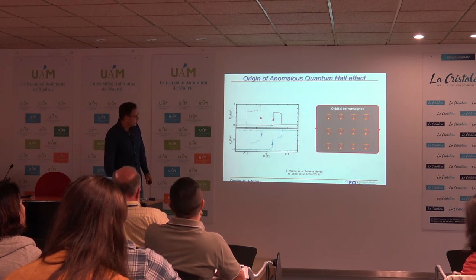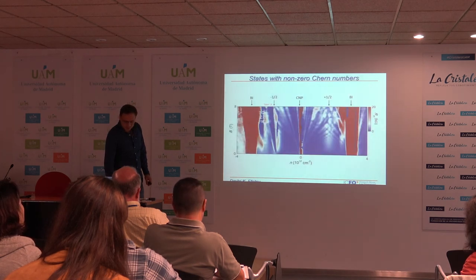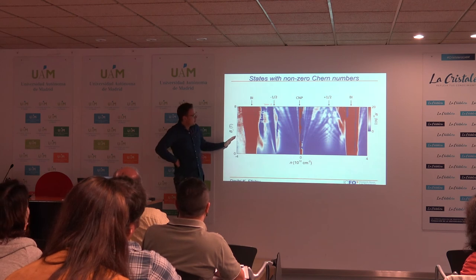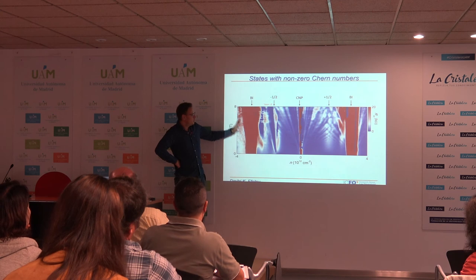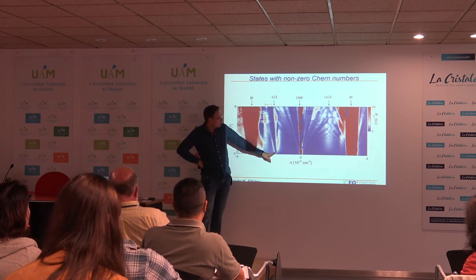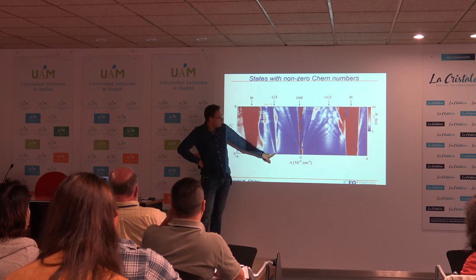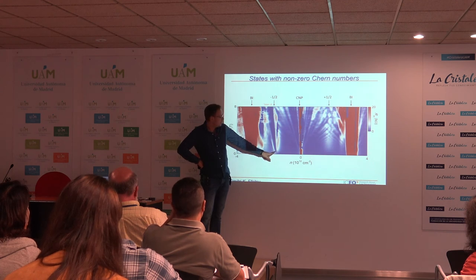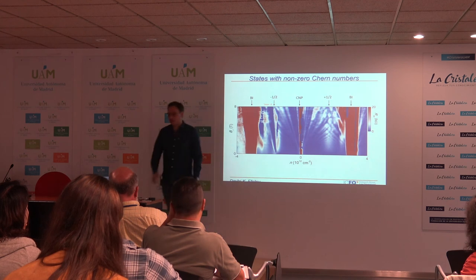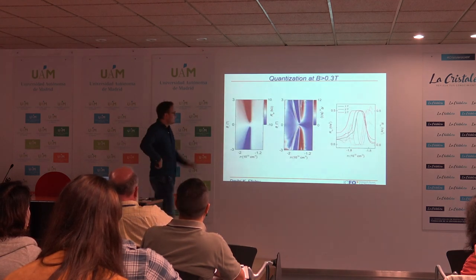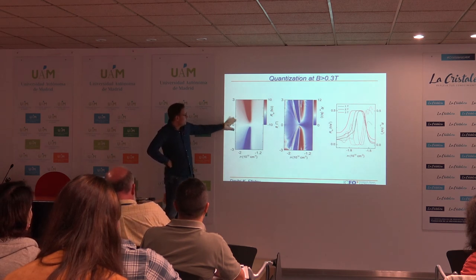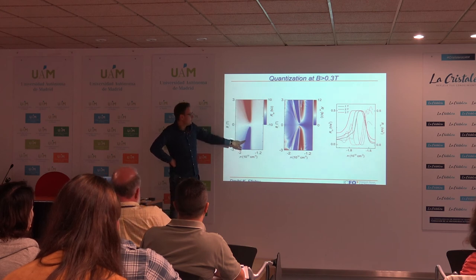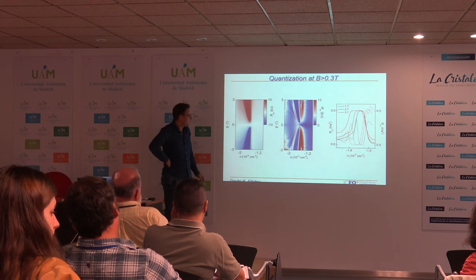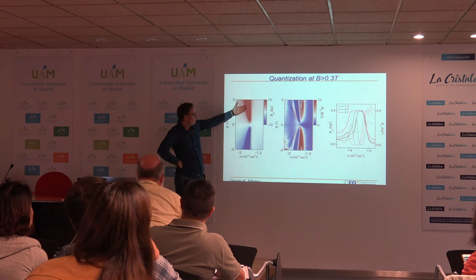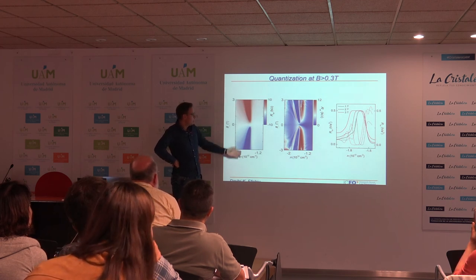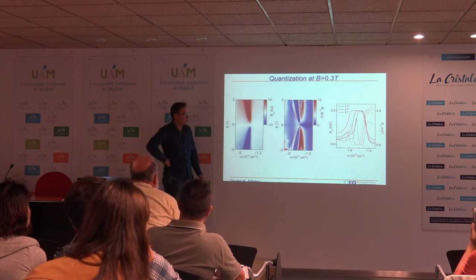Just to touch base on our own data, as I showed in the last phase diagram, we have another sample which has a very similar Landau fan diagram. But in addition, we observe Rxx dropping basically to zero around a filling of minus two, where we don't observe any Shubnikov-de Haas oscillations. We zoom into this region so we can measure Rxy as well. We get almost perfect quantization at these plus and minus two filled states, and as you can see, here we have perfect quantization of Rxy with a Chern number of 2, and if we flip the magnetic field, we get a quantization of minus 2.